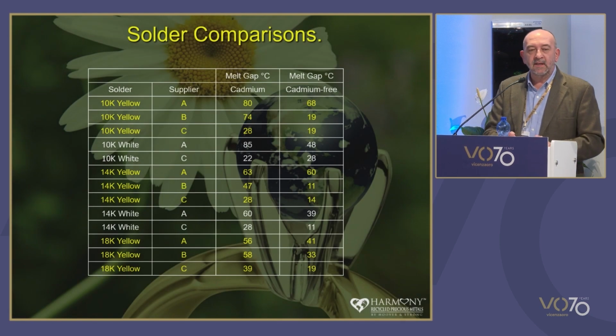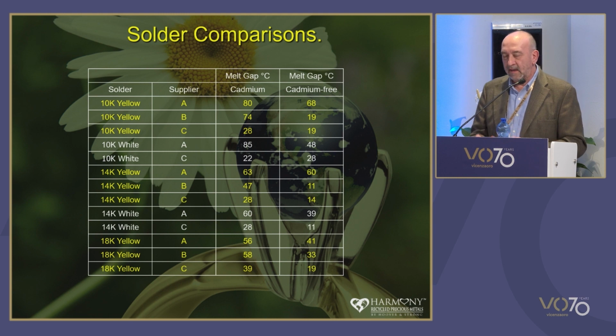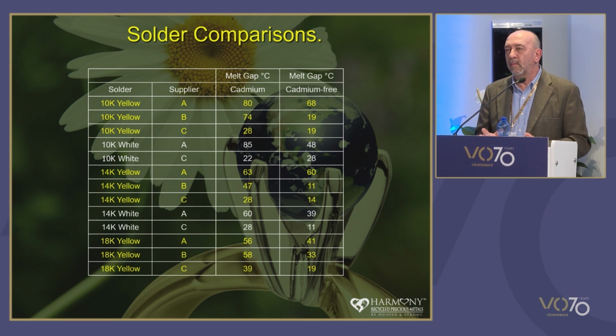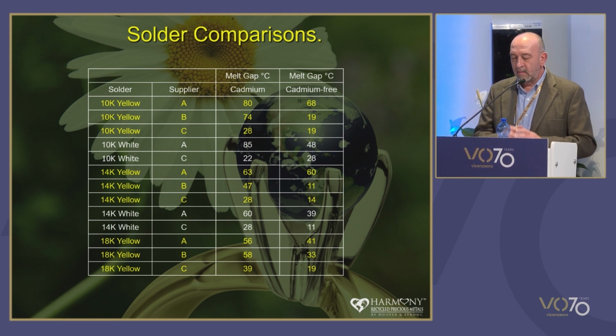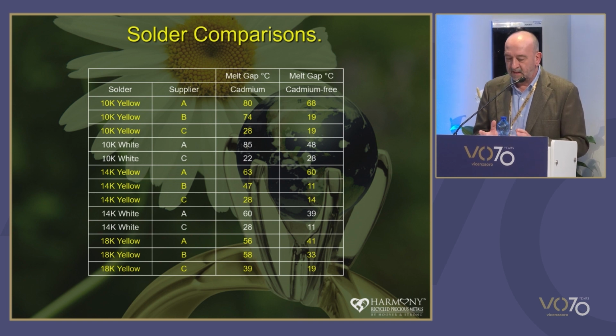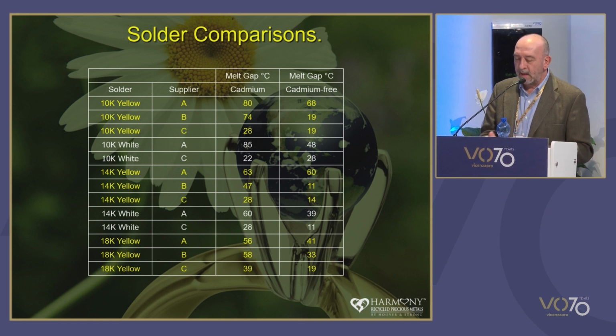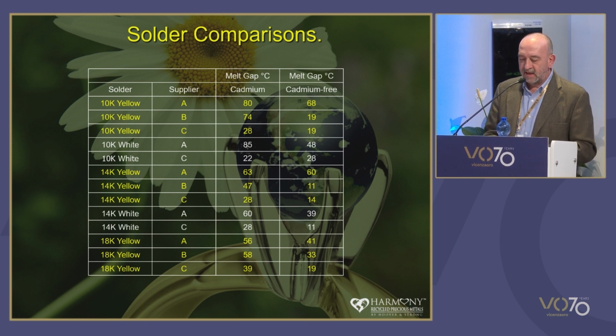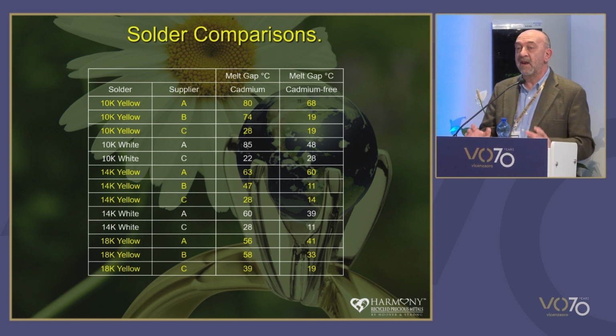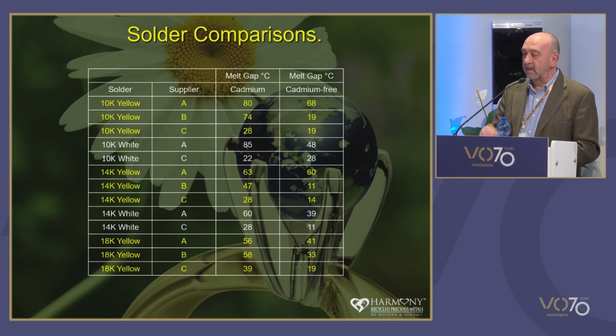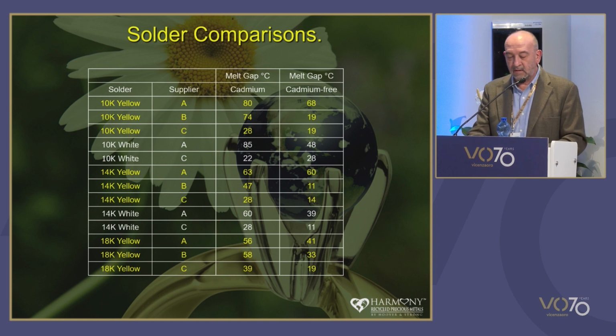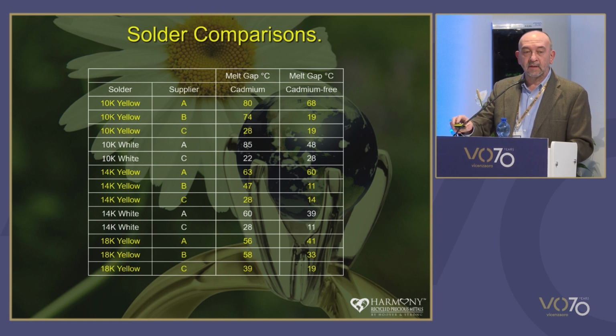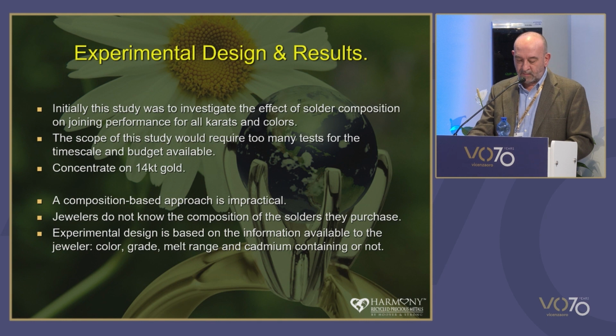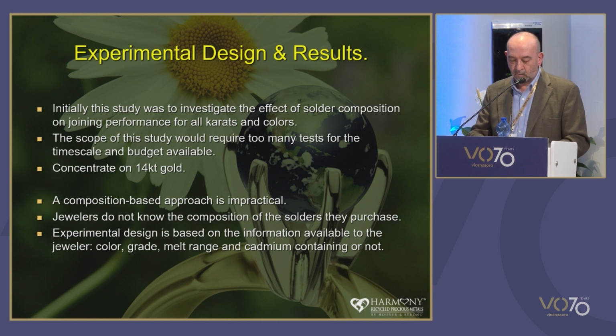So none of this data that a jeweler or a manufacturer gets is composition-based. It's just published data on melt gap, melt range, and whether or not it contains cadmium. Regardless of what else there is in there, all but one example of the cadmium-free solders has a narrower melt gap than the cadmium-containing solders, which should be very beneficial when used in action. So let's have a look at some of the experiments we looked at.